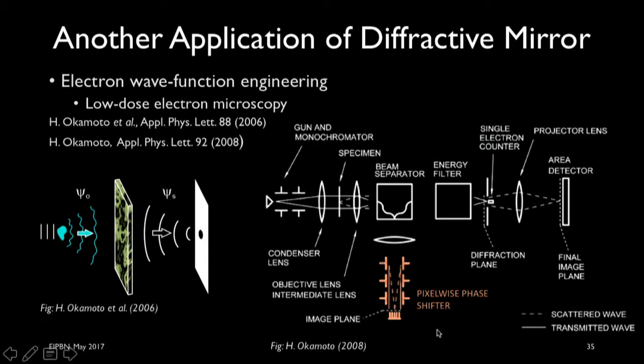So I've highlighted part of this figure that says pixel-wise phase shifter. That pixel-wise phase shifter basically replaces the transmission diffractive element. And Okamoto calls it a pixel-wise phase shifter because he pictures it to be a structure that could be dynamically changed and produce different phase shifts of the electron. So you can imagine an electron coming in from the left, getting separated, getting directed towards this pixel-wise phase shifter, and this pixel-wise phase shifter would impart some complex phase shift on the electron, or modify the wave function of the electron in an arbitrary way. What I've been showing so far is actually exactly that, the simplest case of that, which is a linear 1D diffraction grating, which imparts sinusoidal phase modulations. But this could be as arbitrary as one wants.